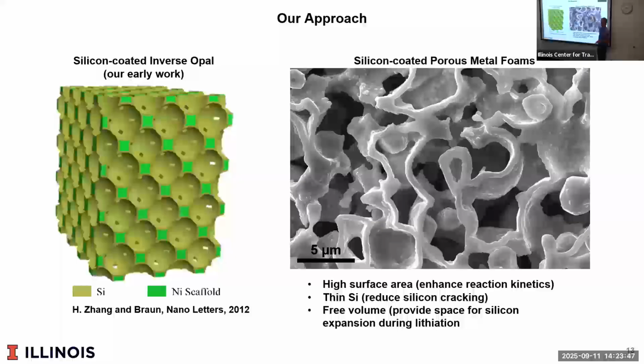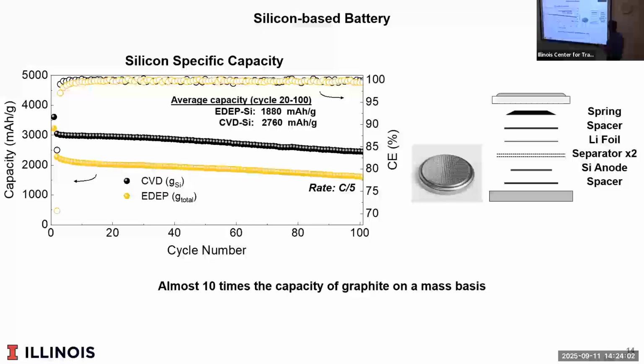So this is a great academic paper, but to become a product, the metal needs to weigh less. This is about 15% metal. I need to get down to about 5% metal. But when you do this right, remember, carbon is down here at 500 milliamp hours per gram. When things go well, we're at sort of 3,000. We're fading a little bit, but we are getting near theoretical. So the idea works, but the foam needs some improvement. But this is just one example. If you could get this to work, you get a 2x increase in your range for the same weight and volume of the vehicle.